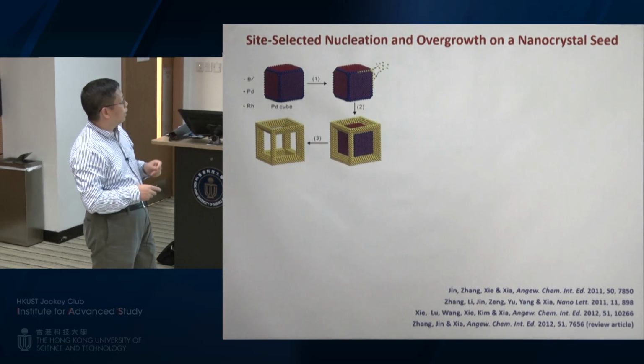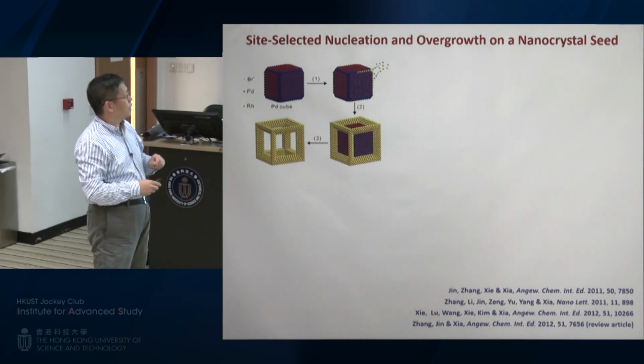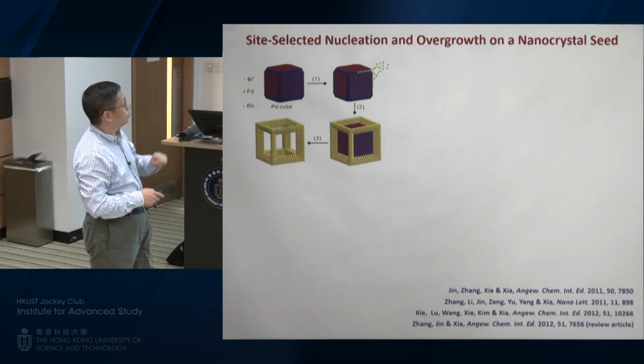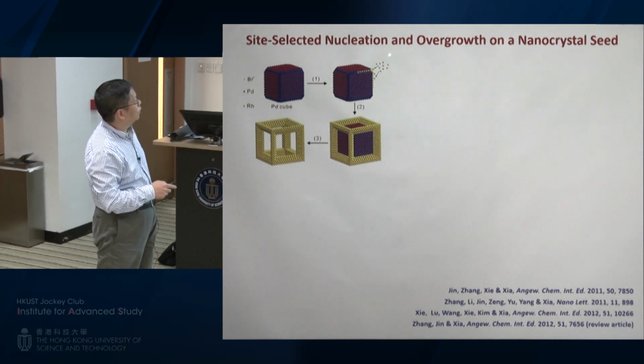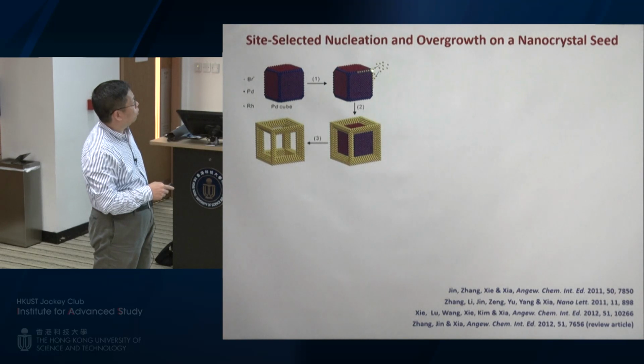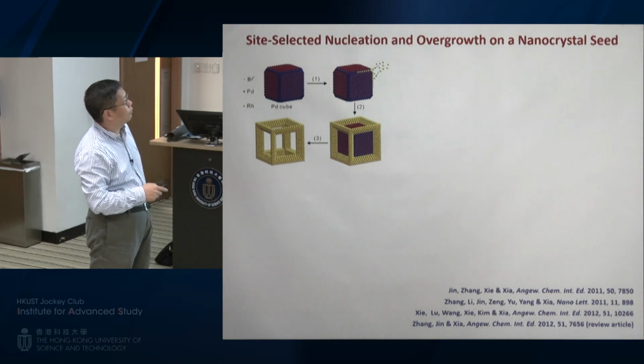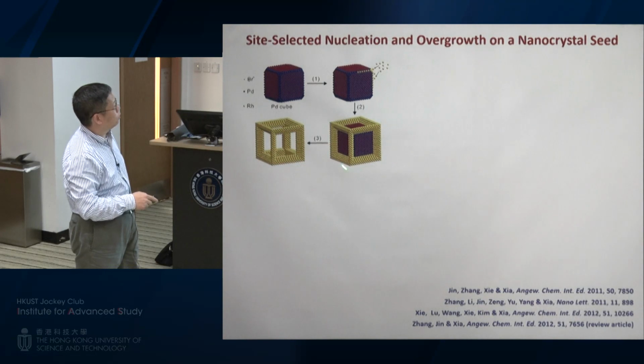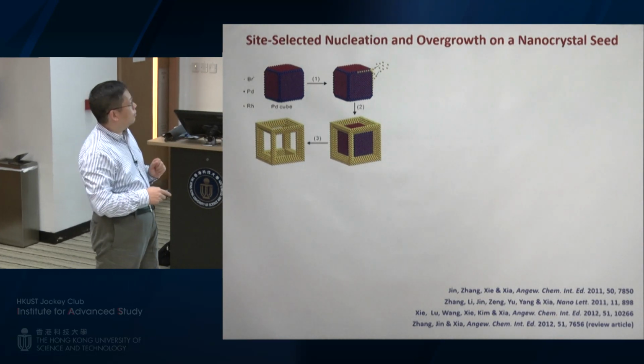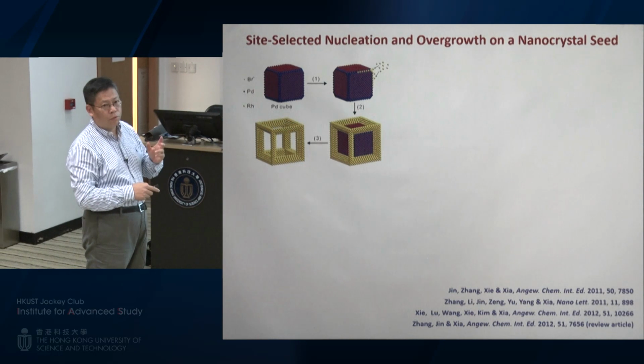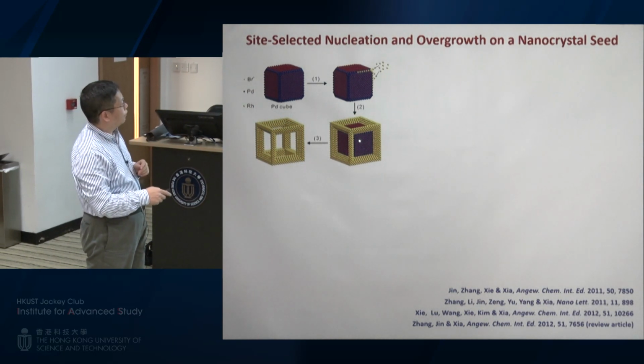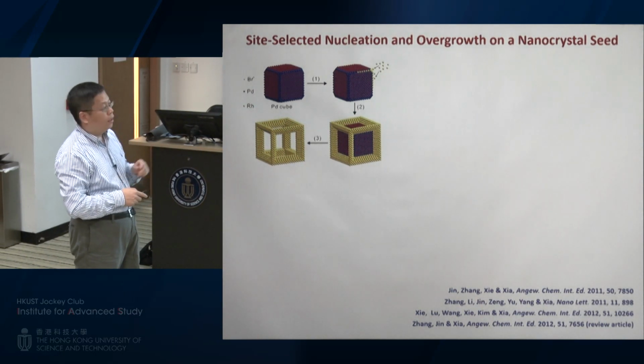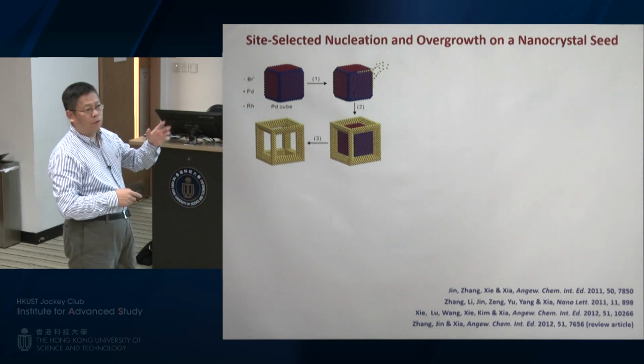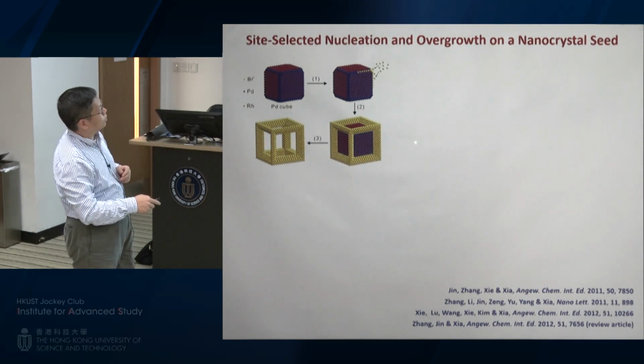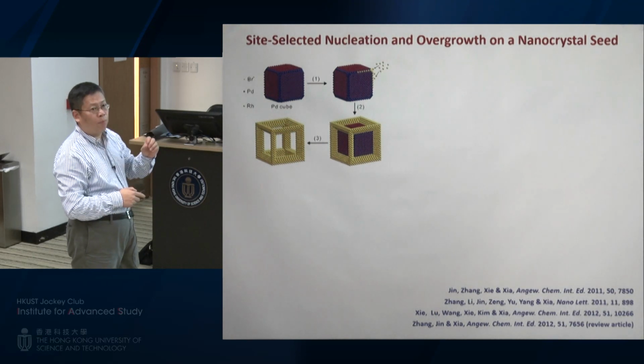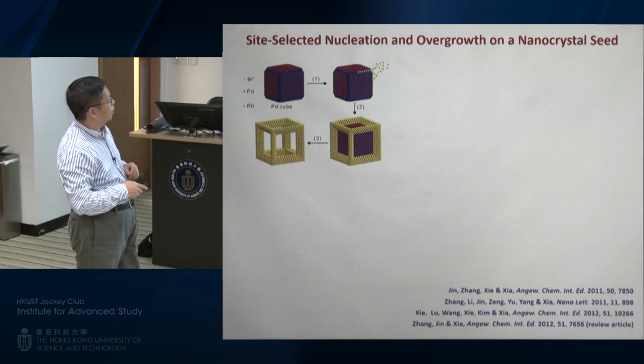So let me just show you two examples in more detail, the core frame and the core shell structures. In this case, you just have atoms being deposited at corners and edges, not the side faces. So eventually you form this so-called core frame structure. And the good thing about a core frame structure is that the core can be removed because the side faces are not covered by the second metal. If they have different reactivity, you can selectively etch away this core. You're going to form this highly porous and open structure called nanoframes.